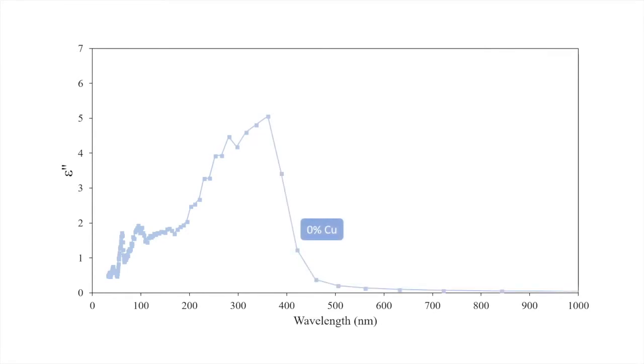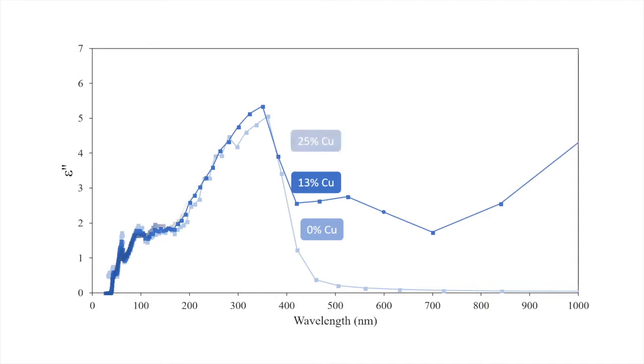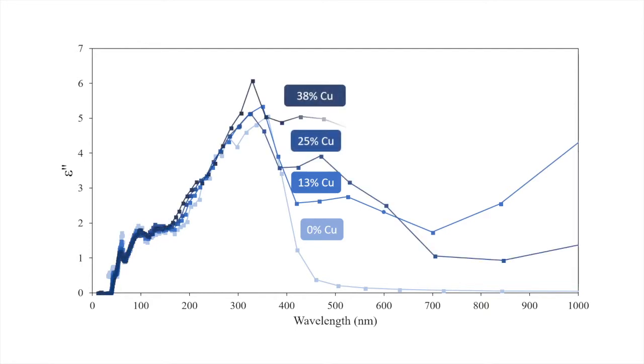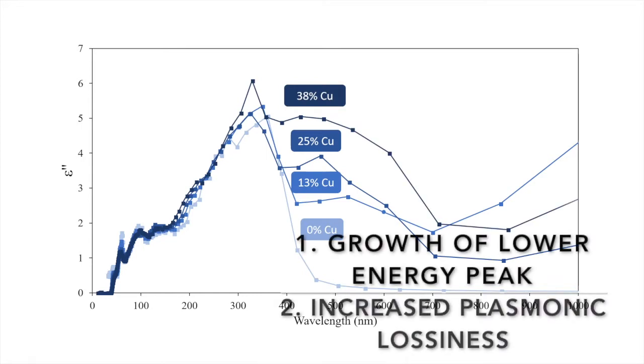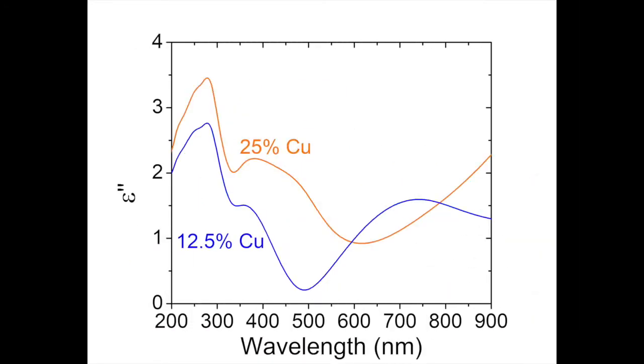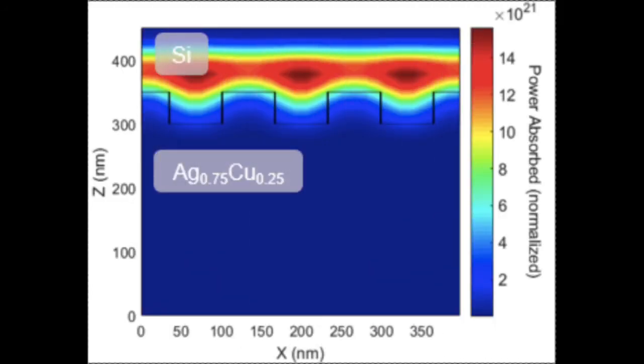We found that increasing copper content from 12.5% to 37.5% has two prominent effects. First, the growth of an additional lower energy peak in the imaginary part of the dielectric function, and second, increased plasmonic lossiness. We observed good agreement between these trends and the trends from our experimental results. In the future, we would like to conduct additional simulations to predict the excitation of surface plasmon polaritons in a full cell.